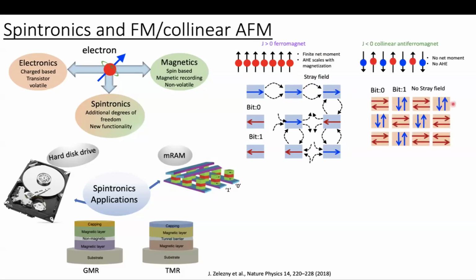In contrast, in collinear antiferromagnet, the net moment is 0, so the data density can be enhanced tremendously because there is no stray field as there is no net moment. But it's difficult to manipulate the magnetic structure or magnetization by external field or external current. But at the same time, in collinear antiferromagnet, the magnetization dynamics is in the terahertz region. So the writing and reading speed will be very fast.